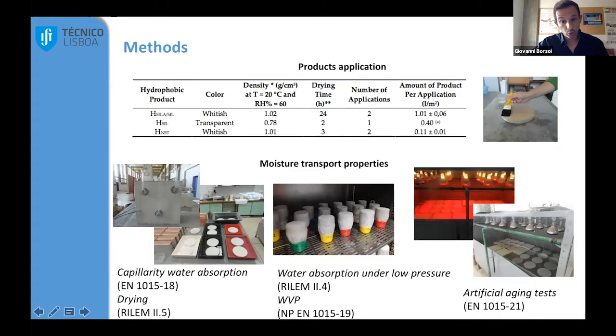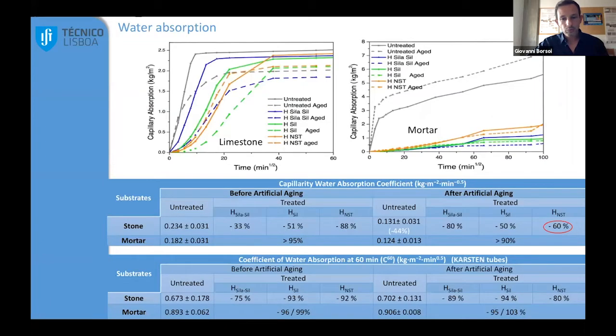Then we focused on the moisture transport properties: the capillarity, water absorption, the drying, the Karsten tubes test, and the water vapor permeability. And finally, we repeated all those tests after artificial aging. So I'm going straight to the results.